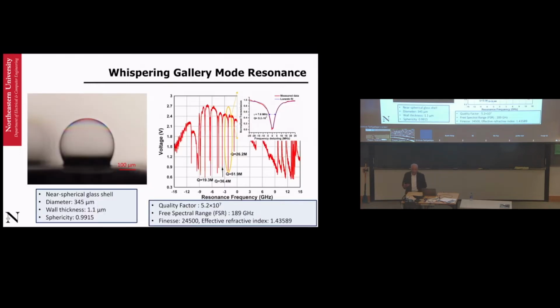So we start looking at all these resonances by doing these scans, and when you look at them, they look like all these sharp dips. These are all the dips where the condition for resonance is met. And as I said, they correspond to different modes, so you can pick your mode carefully so that it's well separated, and you can get some very high quality factors. The quality factor for this particular device is 52 million. So I told you Q is large. So don't expect every system to have a Q of 52 million, okay?